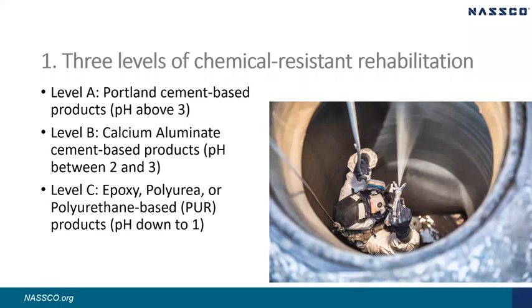Therefore, if you have more moderate acid issues, a level B product may be best. Calcium aluminate cements perform down to acid levels ranging from a pH of 2 to a pH of 3 on the pH scale. Finally, if you have significant corrosion due to microbial-induced corrosion, MIC, or for other reasons, then a level C polymer resin-based solution would be best. These would include your epoxies, your polyureas, and your polyurethanes. They all perform down to a pH level of 1.